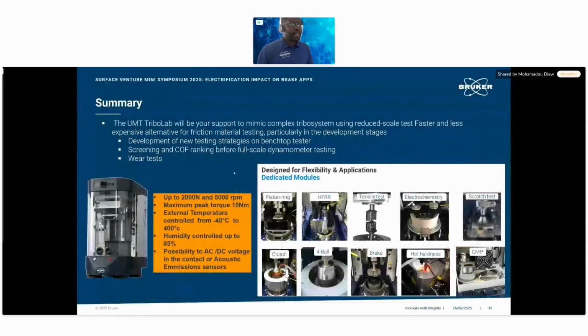What we can summarize with this TriboLab UMT is a system that can go up to 2 kilonewton, 5,000 RPM in rotation, with a maximum peak torque of 10 Newton meter. On this system, we can also control the temperature and the humidity, and have the possibility to add AC or DC voltage in a contact. This is mainly used for lubricant applications, but more and more we will see it because we have a composite material versus steel, and the composite material can sometimes be insulating or create electrostatic charge, which can create other damage that might need to be investigated in the future.